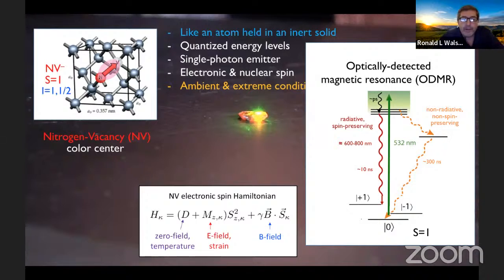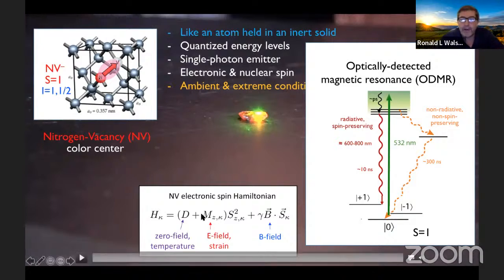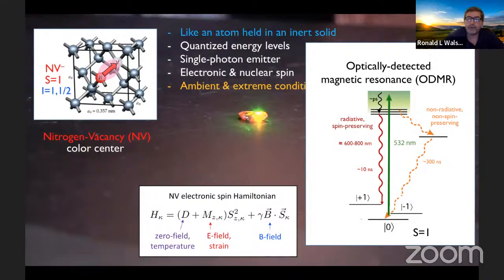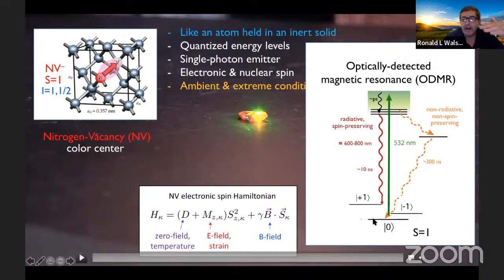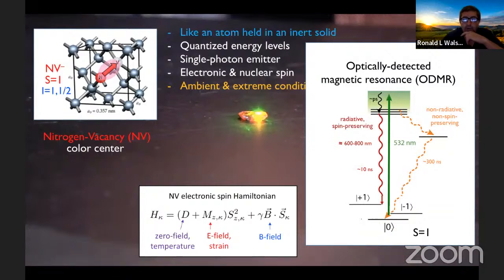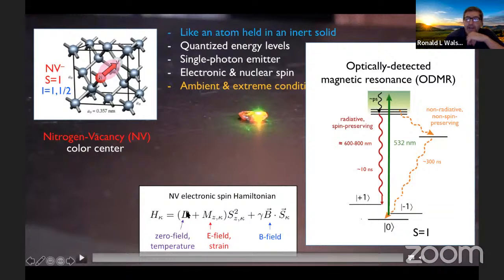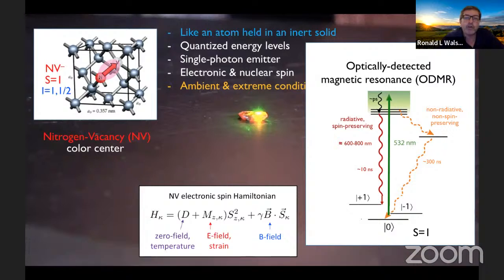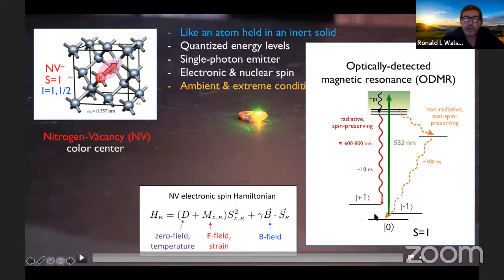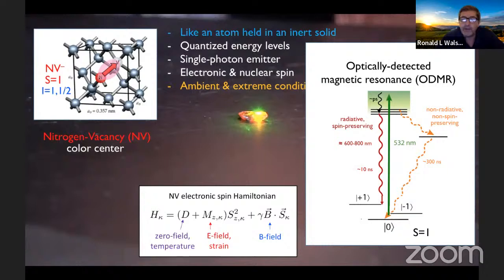First, though, let me note that the electronic spin Hamiltonian in the ground state is summarized by what I show here. There is the zero field splitting that exists in the absence of any applied fields. It's about 3 gigahertz. But that zero field splitting will change slightly as you increase or decrease temperature due to the expansion and contraction of the lattice. The magnetic dipole-dipole interaction between the 2 electrons in the NVs changes. And so the shift in the energy levels of the 0 versus plus and minus 1 due to temperature gives some sensitivity of the NV to temperature, which is the reason why it can be a good temperature sensor.